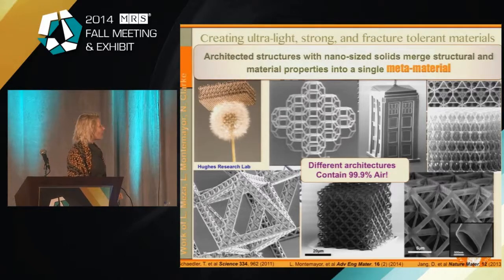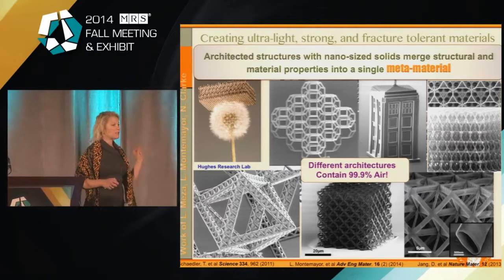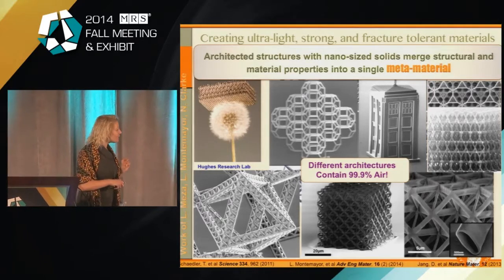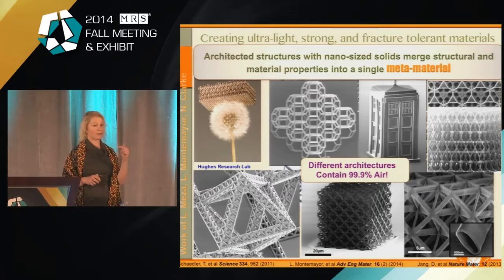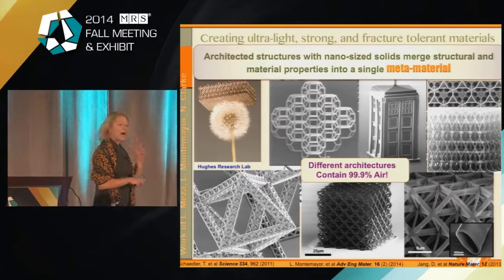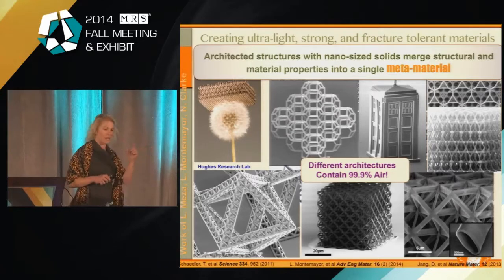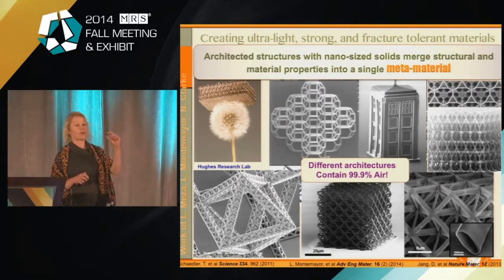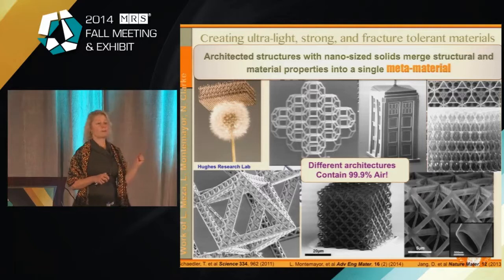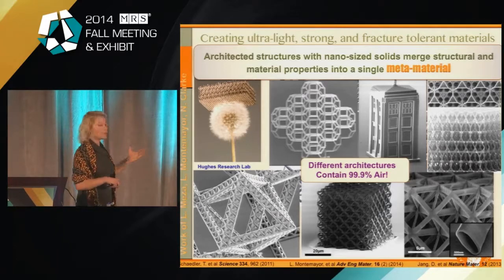So the reason why we're calling these metamaterials now and how they're different from the microlattices is that the size of the unit cell starts to approach the dimensions of the characteristic internal material length scale. So these are all, your eye can't resolve these. If we were to make maybe a centimeter by a centimeter by 100 micron thick little coupon, which is kind of like a little square of a piece of paper, it would look like a cloud sitting on your hand. But it wouldn't crumple like an aerogel would. It's very, very strong. And so your eye can't resolve these features. We're showing you this in the electron microscope, but your eye wouldn't be able to resolve these features.